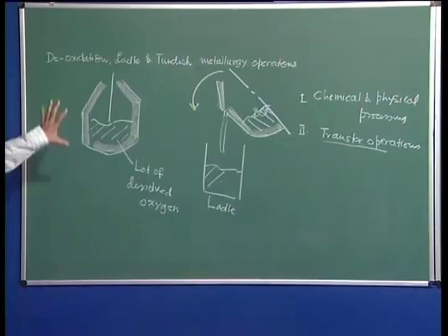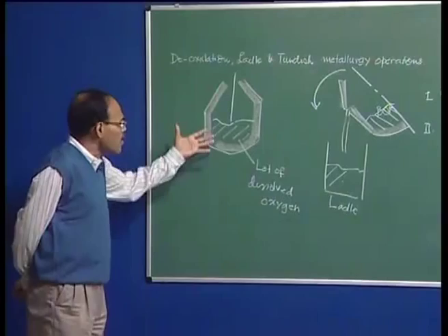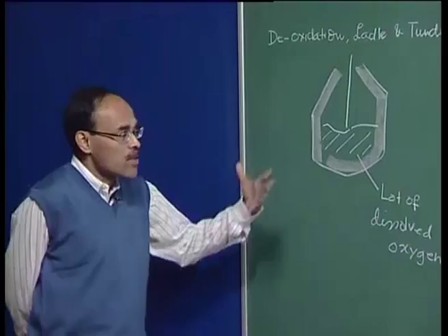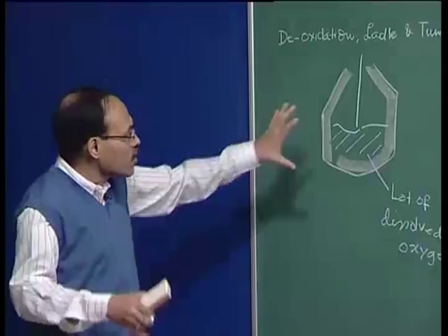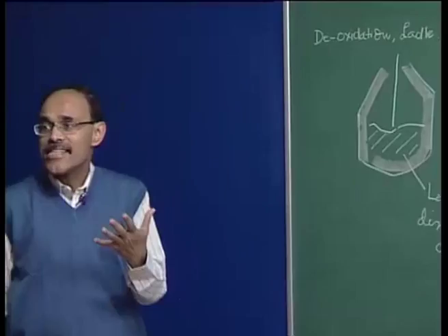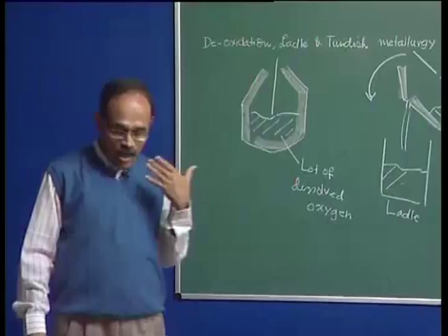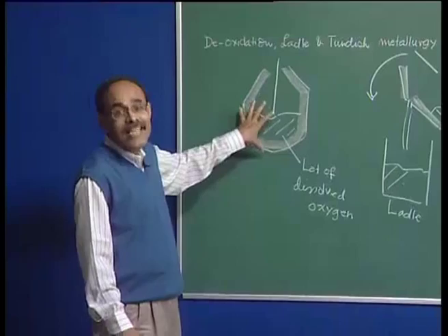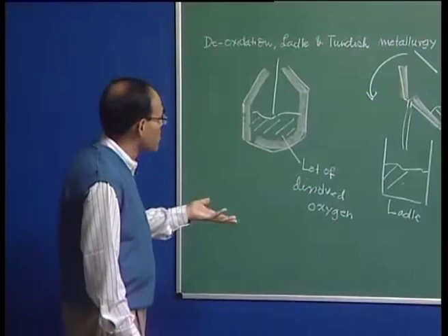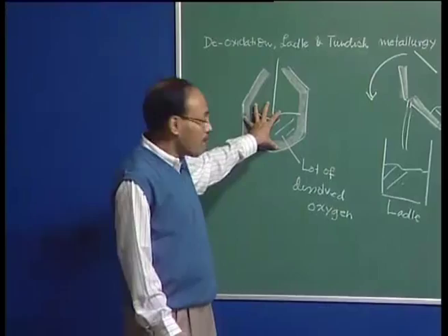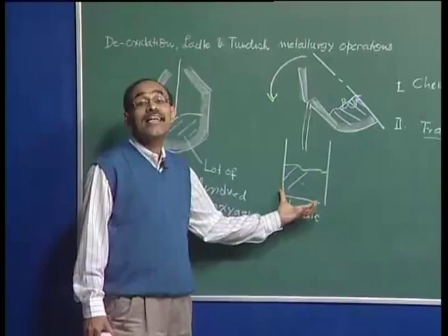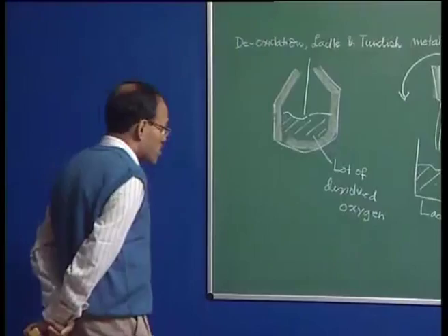So, the objective of primary steel making, as we have seen during earlier lectures, is primarily to decarburize the bath, because if we wish to take care of many other aspects of steel making, for example composition adjustments and temperature adjustments, then unnecessarily the duration of the blow is going to be substantially large. So today the tendency in modern steel making companies is to use this vessel only for decarburization, and subsequent operations like desulfurization or composition adjustment or temperature adjustment can be carried out in a vessel beyond the primary steel making vessel. There, as we advance, we will see the ladle evolve into a very useful reactor which we will call the ladle furnace.